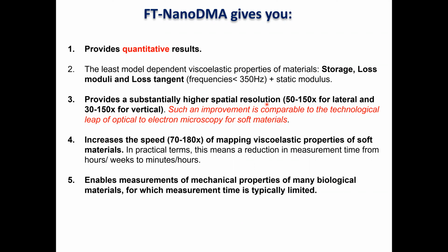If you compare to, I wouldn't say standard, but the more classical way to use nanoindenters, and compare it to a specific state-of-the-art instrument, we have increased lateral resolution up to 150 times, and similarly for vertical. So this improvement is comparable to the technological leap from optical microscopy to electron microscopy for soft materials. So I think that's really interesting. So an increase in speed, even up to higher numbers.